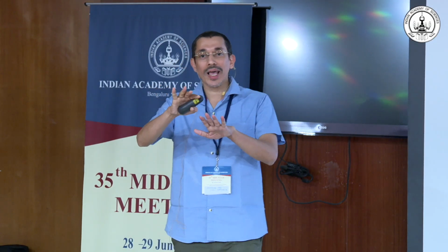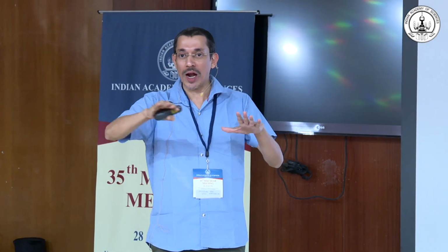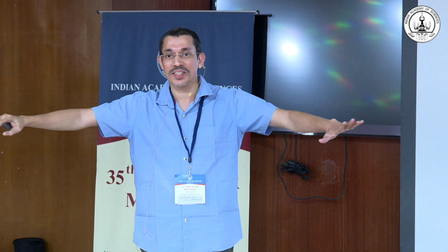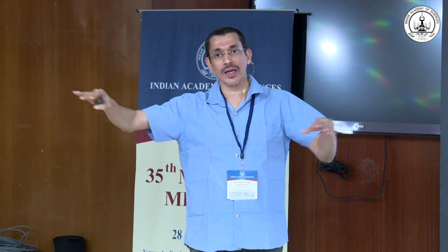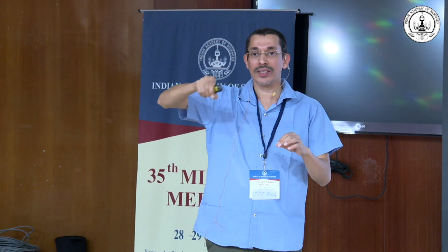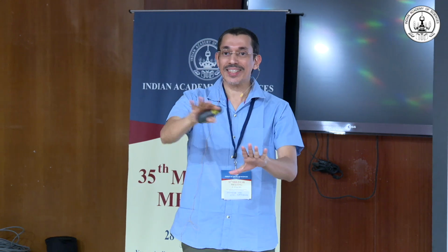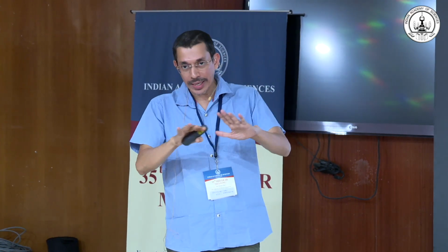It's very interesting. I'm just interested in knowing, whenever you are fabricating this graphene, I believe it can't be the ideal structure. Maybe you are getting just pieces of graphene, right? Is it true? No, I didn't catch. So you are saying it's not an ideal system, the picture I am showing. That is true. As I told you, when I am saying 1.1 degree, in reality there is an angle variation in my system, like a 10% angle variation. People have typically shown this with local measurements like STM. So in that sense, this is not an exactly ideal system, the picture I am showing; you have an angle variation across the sample.